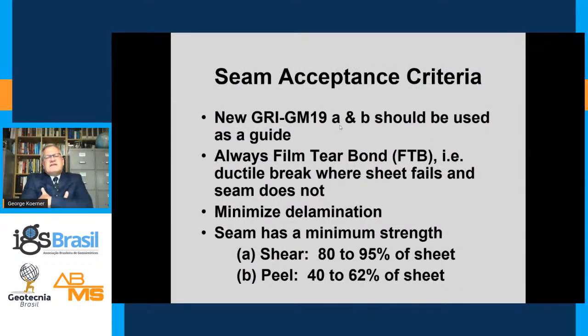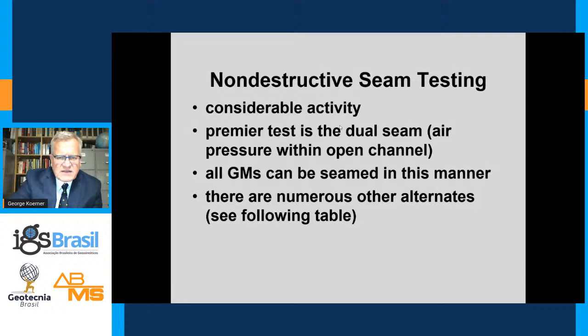Seam acceptance criteria, like I said, is based on GRI GM 19A or B. They're available on our website. You're always looking for a film tear bond, which is a ductile break where the sheet fails and the seam does not. You're looking for minimum delamination, particularly in peel, and then the seam strength, the shear, is 80 to 95% of the sheet strength, the as received sheet strength. The peel strength is anywhere between 40 to 62% of that strength.